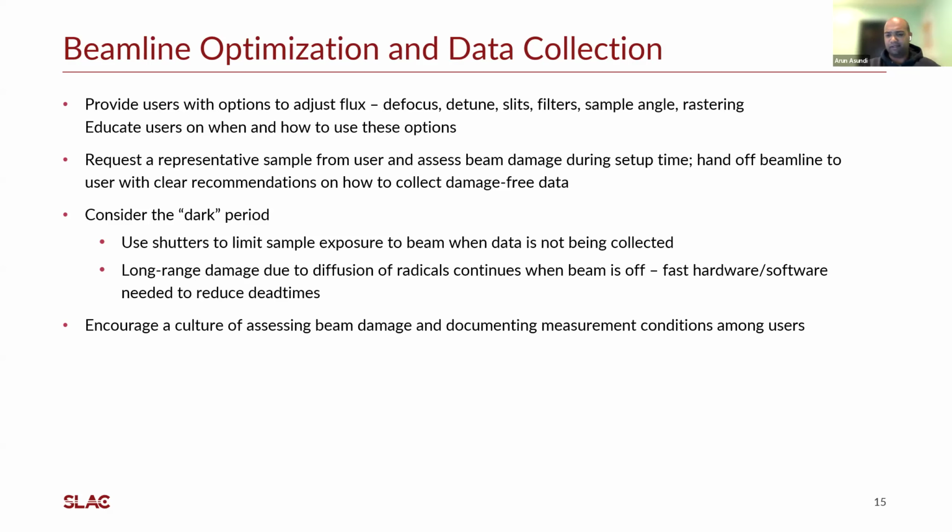I would suggest then that perhaps synchrotron X-ray spectroscopy is maybe not the best first step to characterize these samples. Because there's such a limited amount of time, it's best if users come with some information about at least the concentration of the metals or what they're expecting. If nothing is known about how the sample will behave in the beam, then it's best to err on the side of minimal exposure, at least to start, and gradually increase the amount of sample exposure if it seems like the sample is not being damaged.